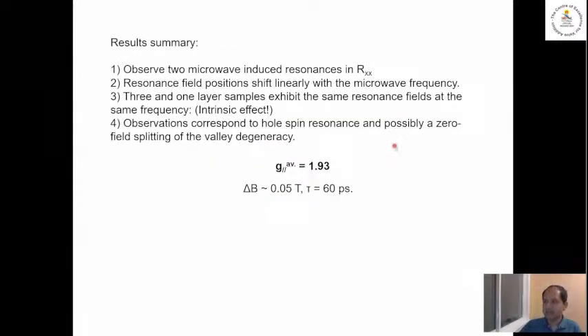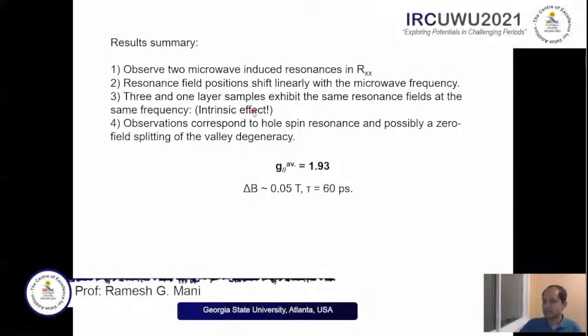Okay, so let me summarize our results. We observed 2 microwave-induced resonances in the resistance of epitaxial graphene samples. These resonance positions shift linearly with the microwave frequency, right? And then we saw the same effect in different samples, which tells us it's some kind of intrinsic effect. And then we said it was a hole spin resonance. We evaluated the g-factor for holes, 1.93. We also, from the width of the lines, extracted a spin lifetime. And we said that maybe we have a zero field splitting of the valley degeneracy in graphene.